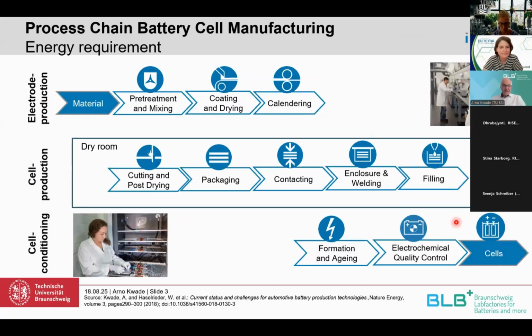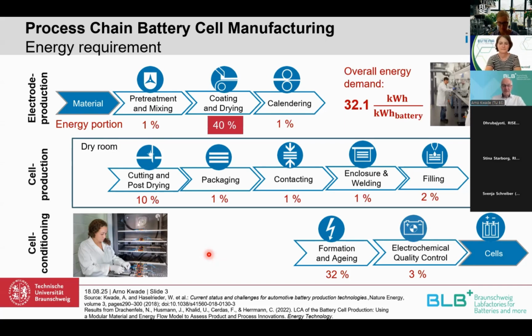Now looking at the classical route, that means wet processing of the electrodes. We have the electrode production with pre-treatment, mixing especially, then mixing wet, then the coating and drying and the calendering, and then the assembly of the cells and the finishing of the cells. I think you all know that. And if we now look at the energy demand for the different process steps, you can see that a lot of energy is required in the coating and drying step. I know that there are also other studies which maybe show 30% of energy, but it's really the biggest part beside formation and aging.